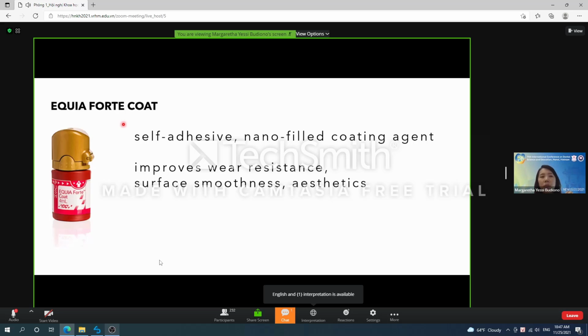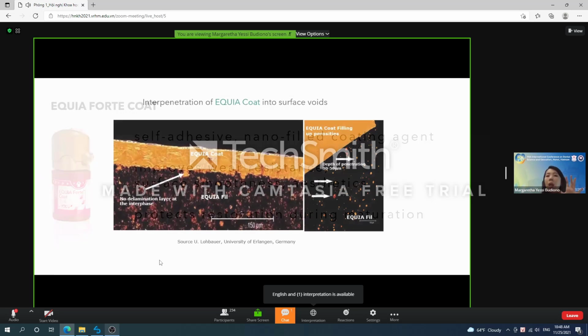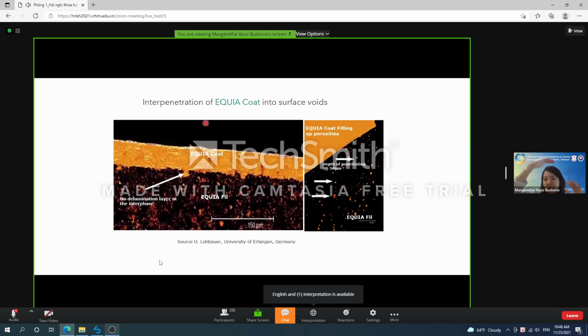But the main function and the main benefit that this coating agent gives to our restoration is that it protects the restoration during maturation. So with GIC or glass hybrid material, once the material has set, there is actually a residual chemical reaction going inside the material until a few months later, and it reaches its maximum strength. So if we protect the material during this initial maturation period, then it can undergo proper maturation process and then reach its maximum strength. And this coating agent, this Equia Forte Coat, it doesn't just sit on top, but it actually trickles down and fills in the surface porosities. So it's kind of like providing reinforcement to this top layer, increasing the hardness, and then creating a more uniform surface so it doesn't break easily.